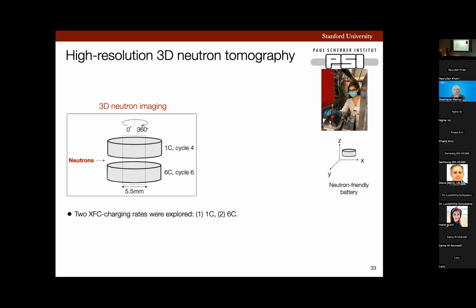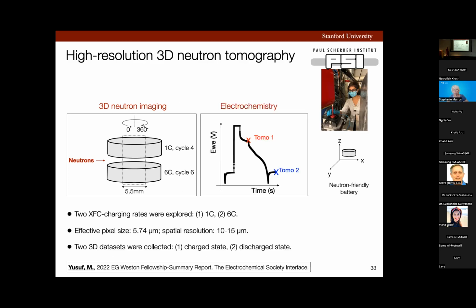Here I stacked two batteries on top of each other as I collected 2D images of a 3D volume, and the stack rotated from 0 to 360 degrees. Here I explored two charging rates, 1C and 6C, where 6C corresponds to a relatively faster charging rate as compared to 1C. My pixel size was 5.7 microns and spatial resolution was around 10 to 15 microns. Now this is important because I mentioned the relevant length scales earlier in my talk. So this resolution meant that I was able to detect lithium micron scale deposits in a full cell battery. And the data was collected of the batteries in the charged and then in the discharged state.